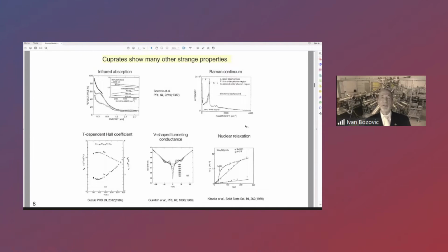The ones that I'm familiar with are infrared absorption, electronic Raman continuum. Those in good metals die out on a scale of, let's say, 50 inverse centimeters, which may be like 4 or 5 millielectron volt. And the reason for that is that the momentum is well defined in one band and in the other band, and the momentum of light is basically 0, so the transitions are vertical. That's why with the momentum, the infrared absorption dies very fast in metals, and so does electronic Raman continuum. But in cuprates, both of these extend to at least 1 electron volt and beyond.